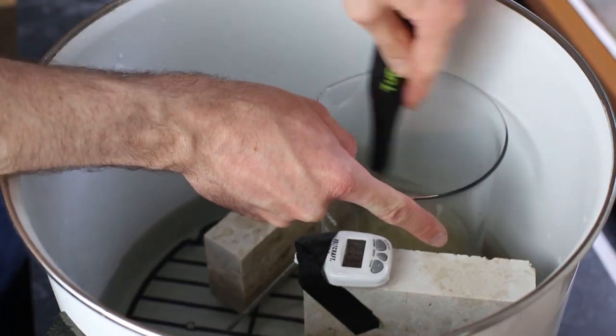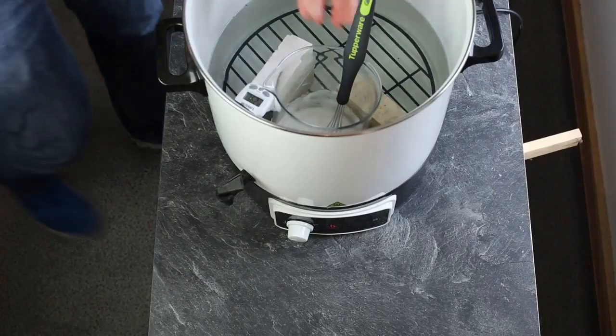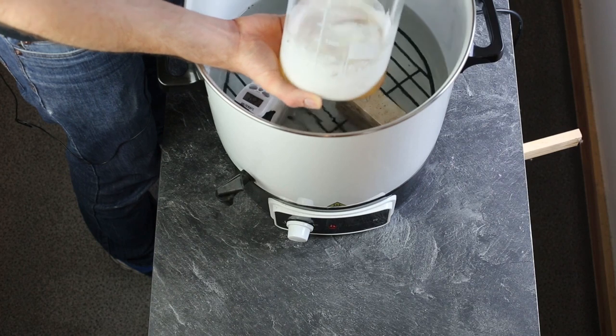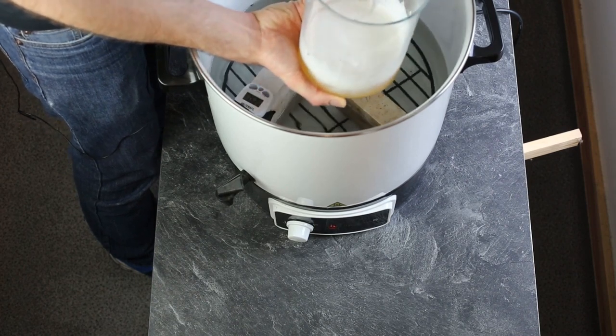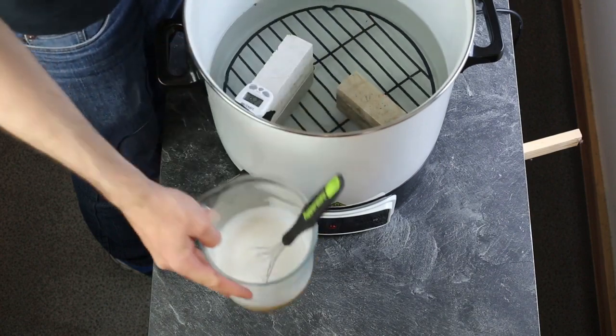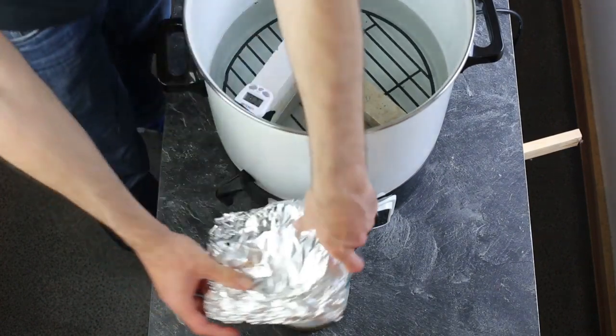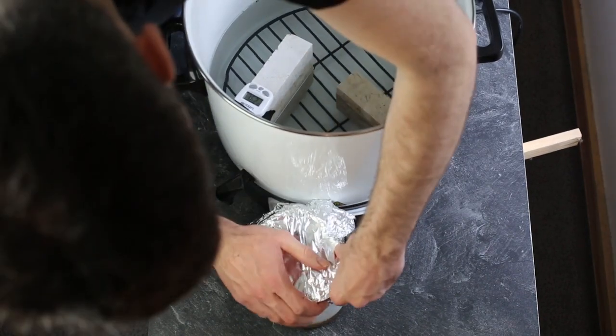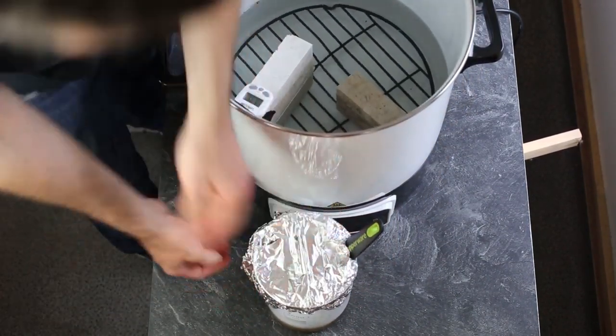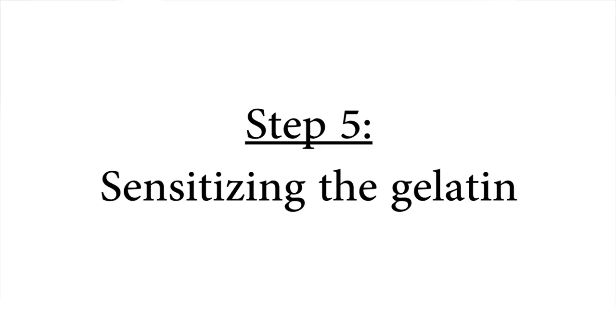If you accidentally heat the gelatin above 50 degrees Celsius, throw it away. High temperatures damage the structure of the gelatin and result in a bad coating. Keep the temperature at 40 degrees and stir the gelatin every 5 minutes for a total time of 1 hour. After 1 hour, the gelatin will have dissolved completely and will have turned into a honey-like solution. Take the beaker out of the water bath and let the gelatin rest for 12 hours.